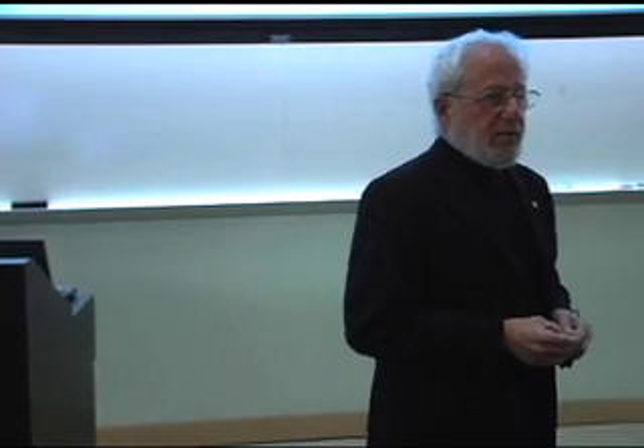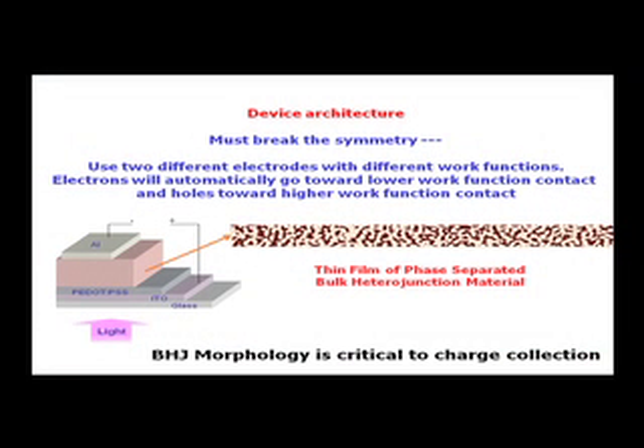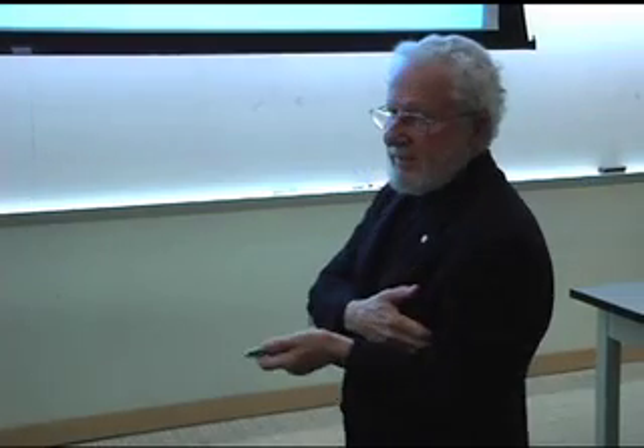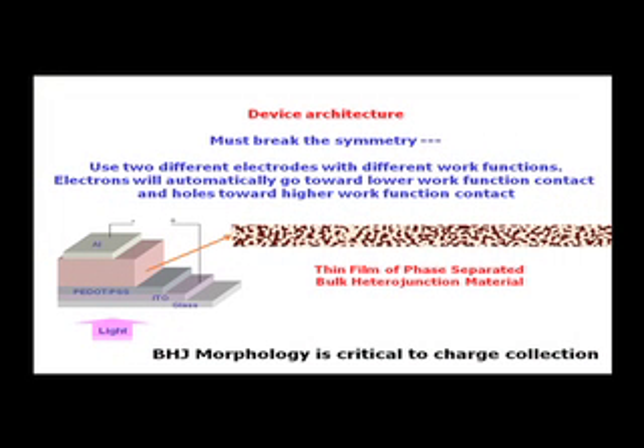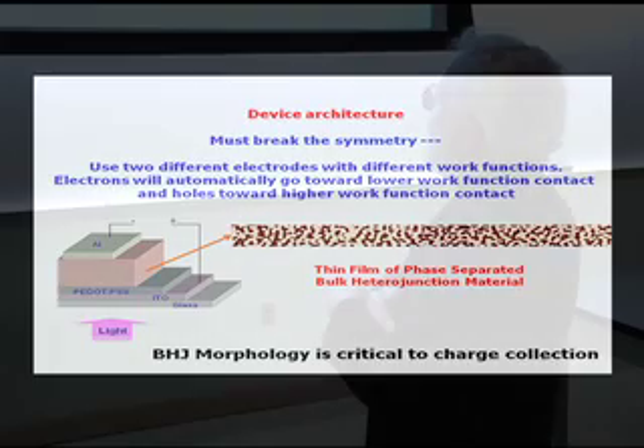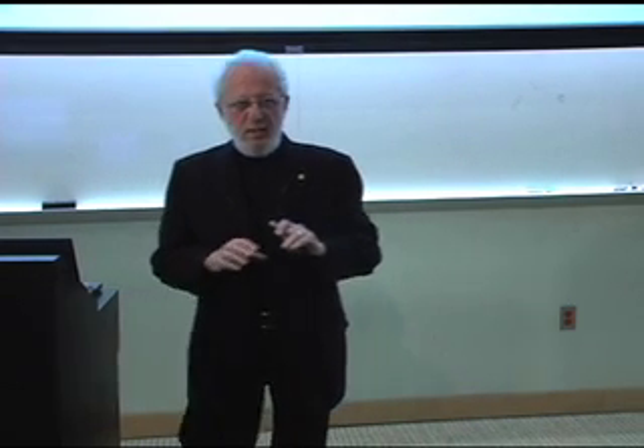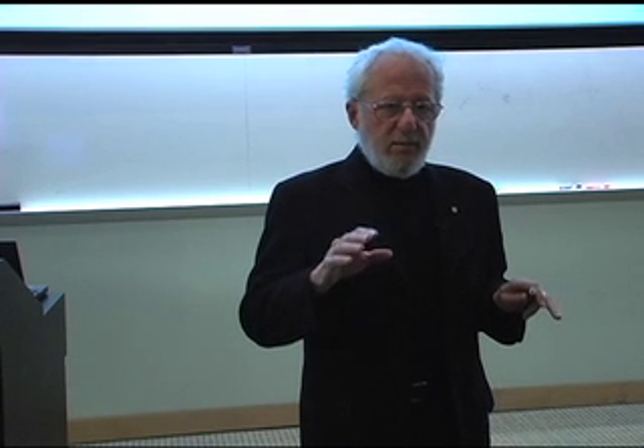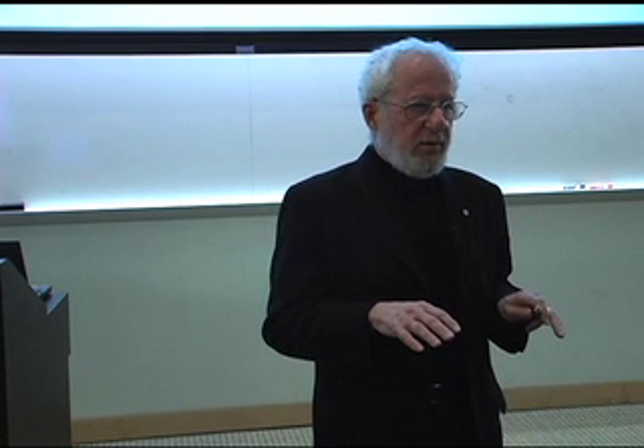Now I want to make a device. The device, in fact, is really quite simple. I want to put this bulk heterojunction material between two electrodes so that when I come in with a photon and I separate the charge, electrons will go to one side and holes will go to the other side. In order to do that, I have to tell the electrons which way to go, because up and down are the same. So I break the symmetry simply by using two different metals, a low work function metal on one side and a higher work function metal on the other side. And the electrons will always go toward the low work function side, and the holes will go to the high work function side. So the fabrication is simple. On the nanoscale, it's done by spontaneous phase separation, and on the macro scale, it's done by using two different materials for electrodes. Now, of course, I'm purposely exaggerating, but the essence of what I said is true.